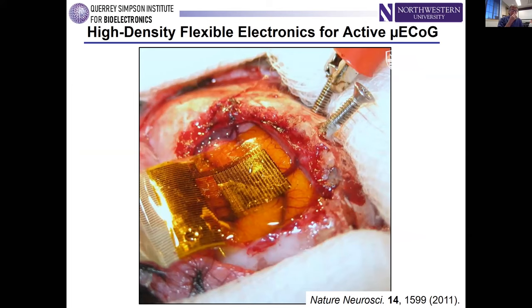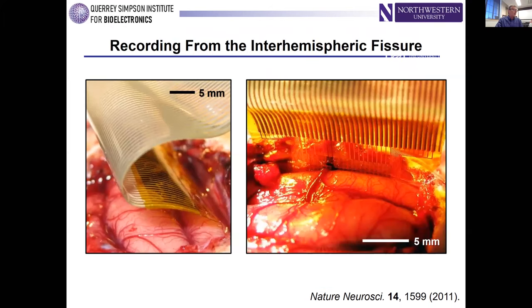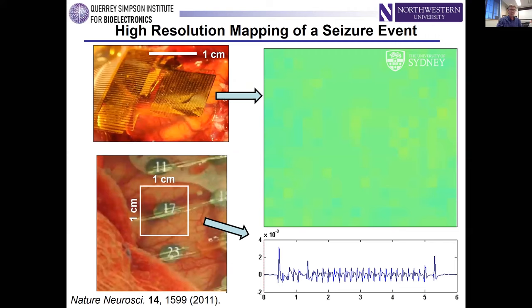And this is a feline model of epilepsy. This is through a collaboration that we had with neuroscience researchers at University of Pennsylvania. And so this is providing the highest resolution mapping of neural activity on the surface of a large mammal animal model that's possible and enabled by the silicon nanomaterials in the backplane of electronics. As I mentioned before, you can not only map the surfaces, but also hidden surfaces. You fold it in half. In this case, we plunged it down into the fissure between the right and left hemispheres of the brain of this feline model. So you can do sort of unique things as a result of the extremely high levels of bendability of the electronics. And so this is sort of what it looks like.